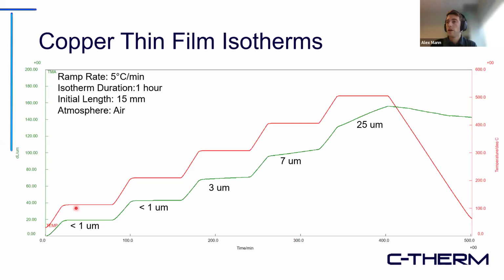We can see here that during the first two temperature holds, the expansion stopped. Makes sense, temperature's the same, no thermal expansion. But once we get to around 300, we see that although the temperature didn't change, we did see a little bit of expansion. Then up at 400, during the hour-long isotherm, we see a little bit more. And all the way up at 500, we see that even though the temperature wasn't changing, the sample was still deforming.